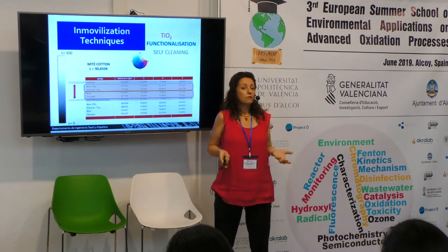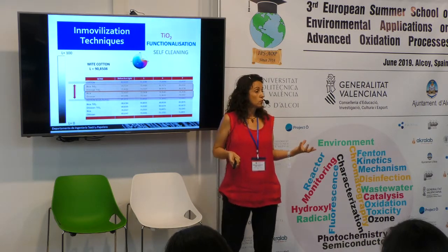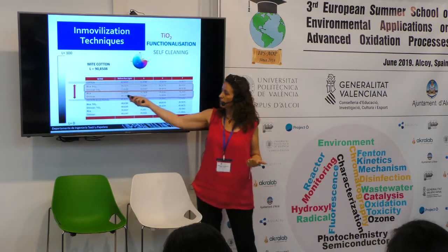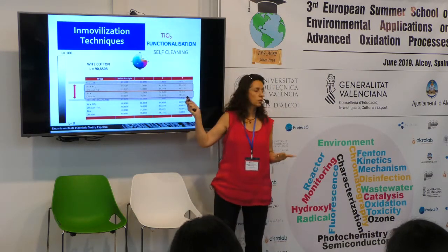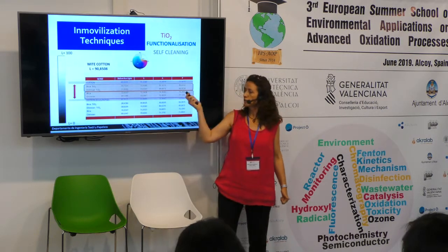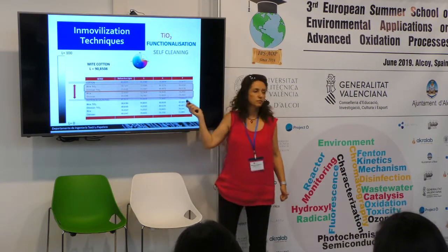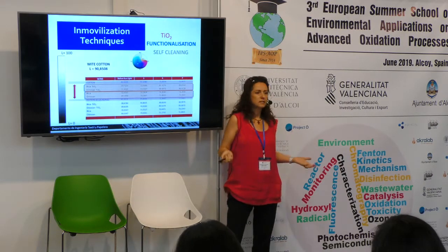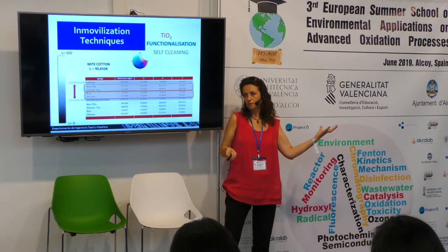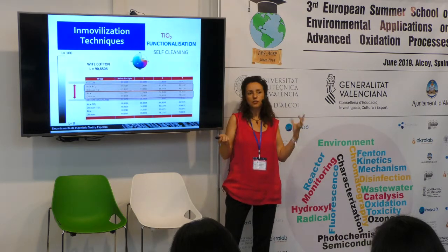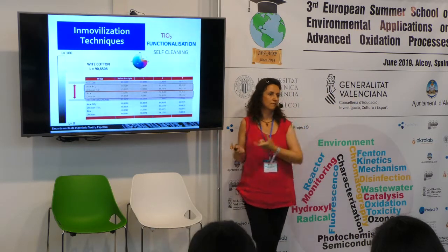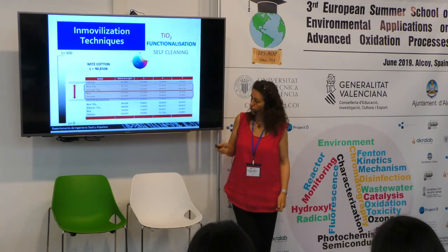Does it happen when I have the cotton with the binders without titanium dioxide? We can check on this second part that no. After 7 days, I move from 72 to 76 or from 69 to 72. So in that case, the effect is due to the titanium dioxide, okay? And then we have a reaction between the wine stain and the titanium dioxide.